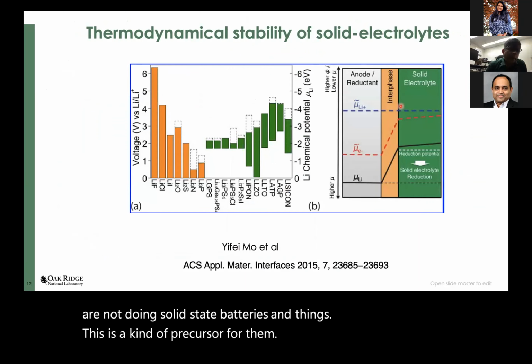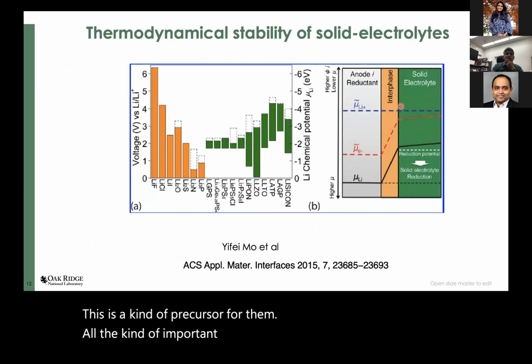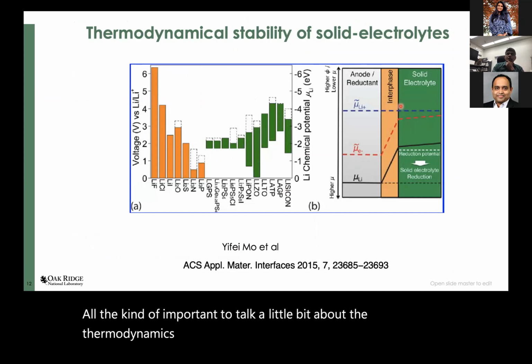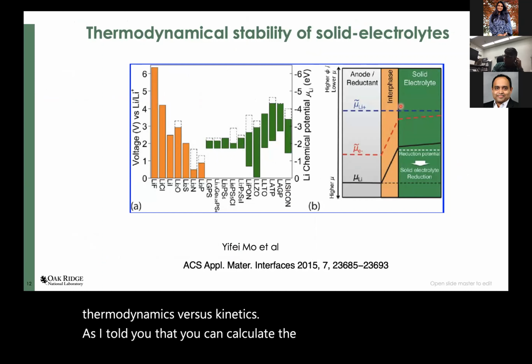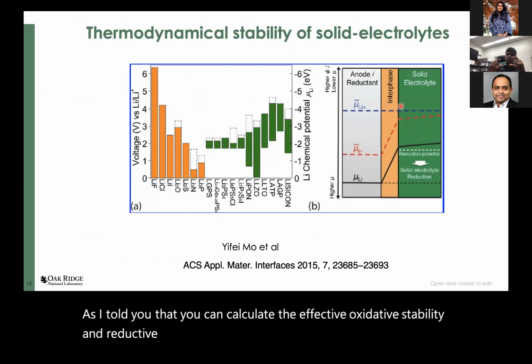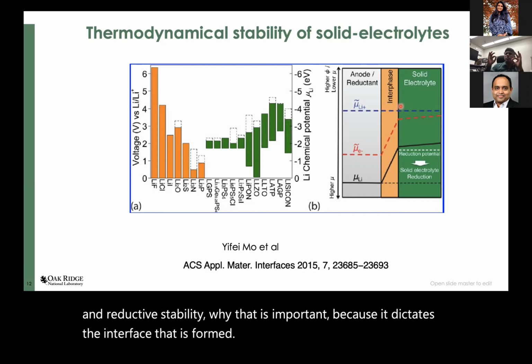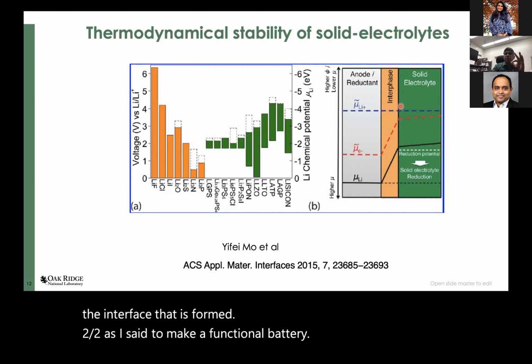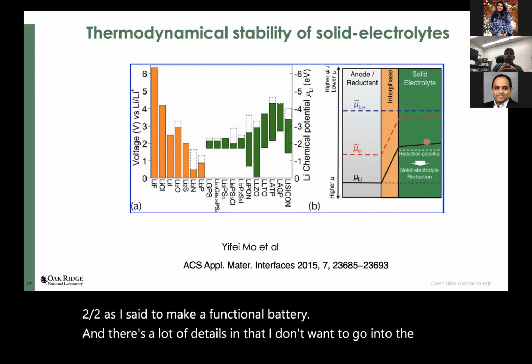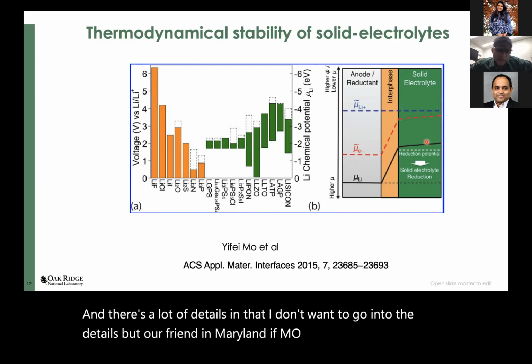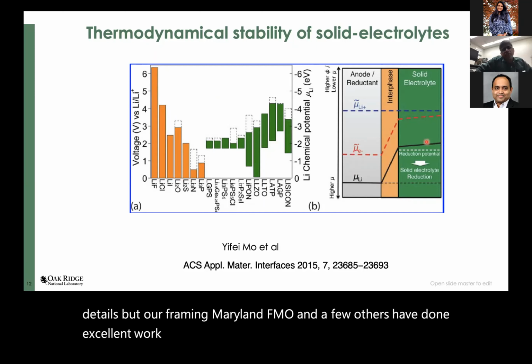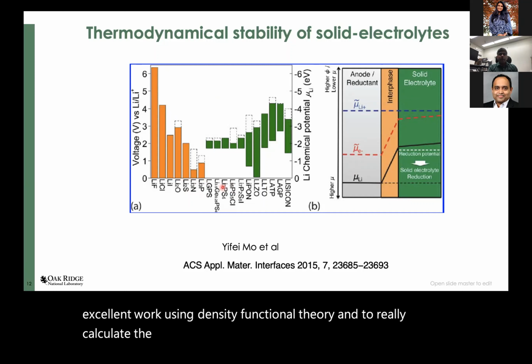Now, it's important to talk a little bit about the thermodynamics versus kinetics. Now, as I told you, you can calculate the effective oxidative stability and reductive stability. Why is that important? Because it dictates the interface that is formed to make a functional battery. And there are a lot of details in that. I don't want to go into the details, but our friend in Maryland, Yifei Mo, and a few others have done excellent work using density functional theory to calculate the electrochemical window of a series of important LLZO, sulfides.